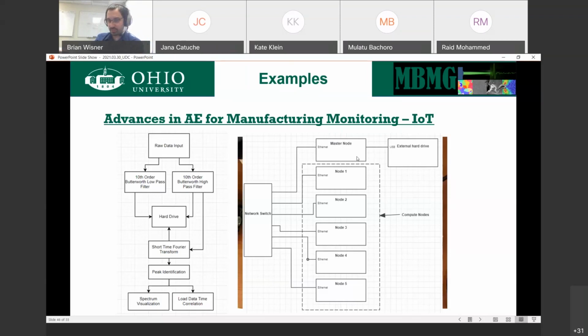Once we have that, the rest of this is just a series of nodes, basically set up the same way you would set up a cluster for any other type of computing. And we can delegate each one of these nodes to do a specific process. So node 1 could do the low pass filter. Node 2 could do the high pass filter. Node 3 could be doing peak identification. But the benefit here is I can add as many nodes as I want. And if for some reason node 3 fails, I can have a backup, say node 4, which was just sitting there, replace node 3. So you never lose processing time.